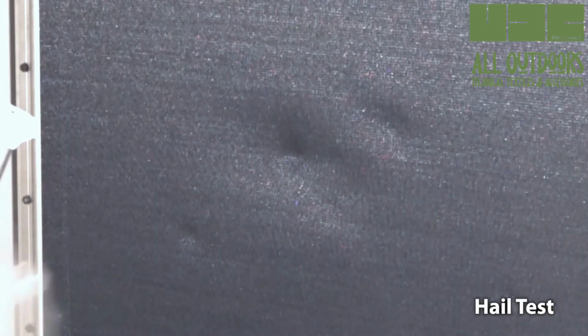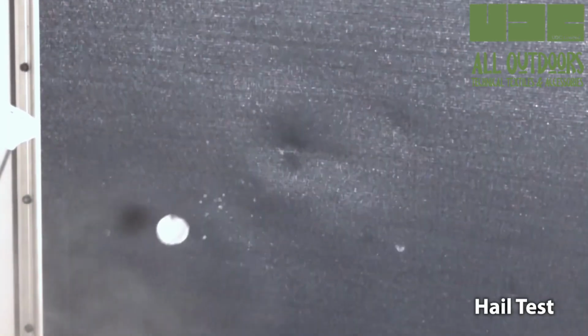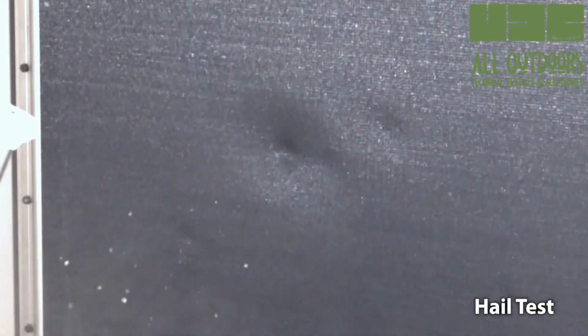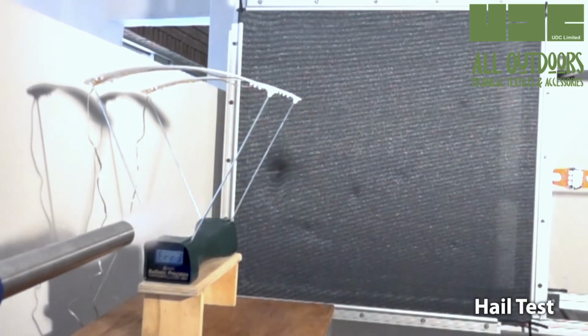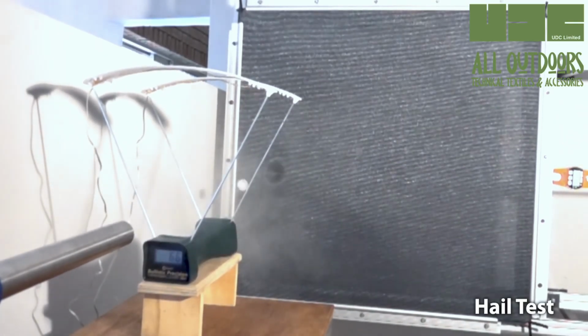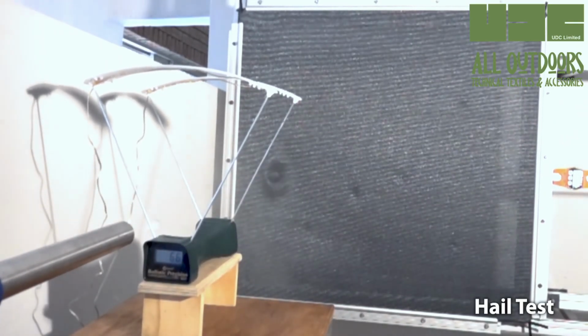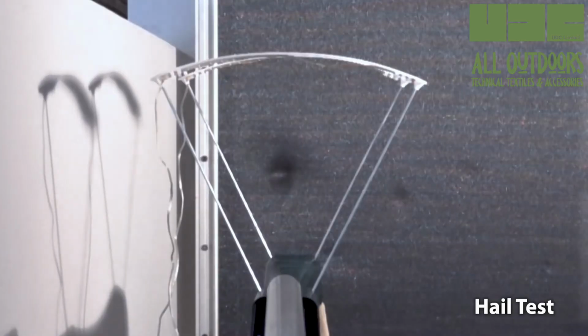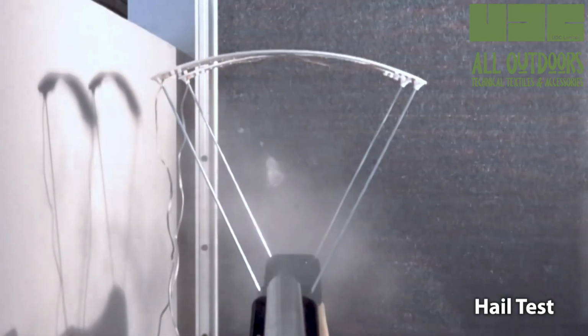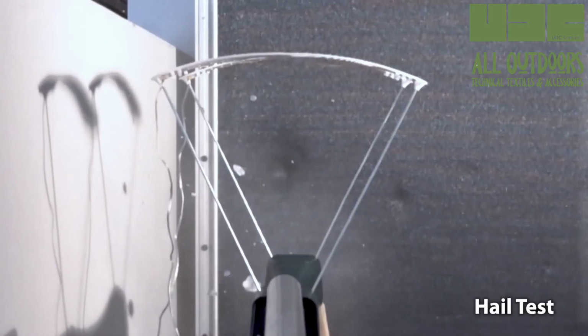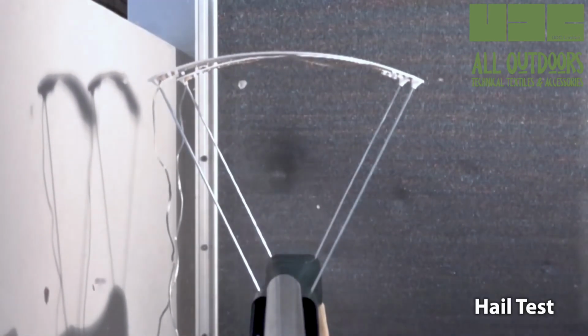We started the test by firing the ice balls at the fabric at 56 meters per second, or 210 kilometers per hour, and went up to 76 meters per second, or 275 kilometers per hour. The maximum velocity achieved was unfortunately not accurately recorded by the Caldwell Ballistic Precision Chronograph. The fabric returned to its original shape and tightness soon after the tests were completed.